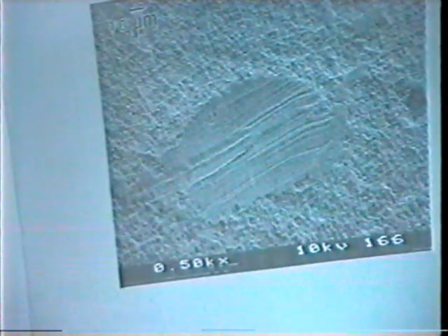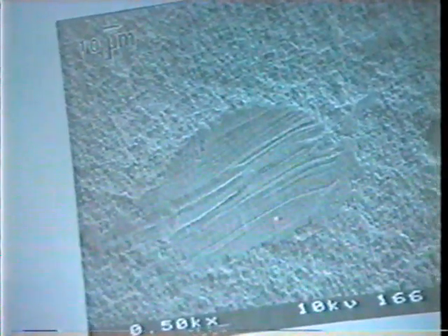Okay, now, as I said, the titanium erodes in this experiment. We only saw this once, but it gives you an idea what I'm talking about. The original surface looks like this. In this electrode, this patch was passive, and all the rest of it was active and eroded. I only remember seeing this once, but that's what the original surface would look like.